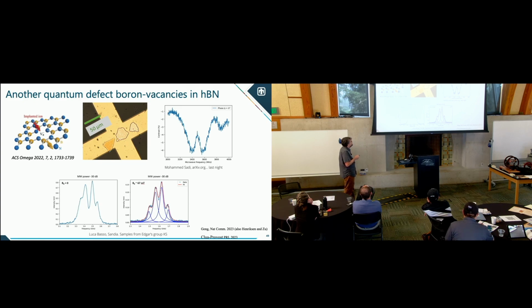What we actually did, we had an experiment where we were trying to do spin polarization experiments, but this is an hBN flake with boron vacancies. We make those just by helium bombardment. So in that case, you're just looking to knock out the borons, right? You don't have to dope it, you're just doing damage. And you can actually do a magnetic ODMR type spectrum. This one doesn't look that great. A lot of it is because of all the nuclear spins around.